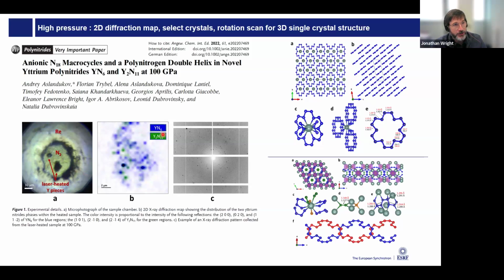They make an image of the sample by scanning the X-ray beam across the sample and do a powder diffraction snapshot at each point as they scan across with the beam. Then when they look at this data, they're sitting live at the beamline and they'll decide, okay, I want to measure the single crystal data for this specific crystal here, or for that specific crystal there. And they can go and choose a crystal from their diffraction map.